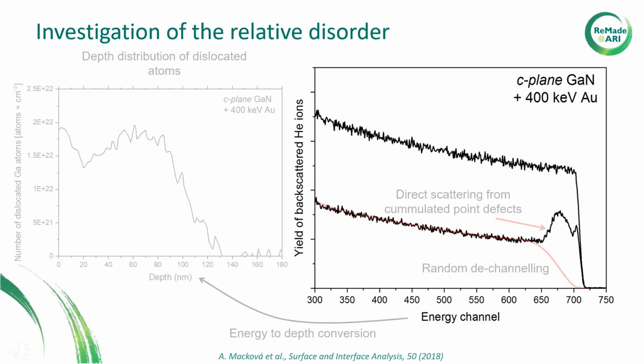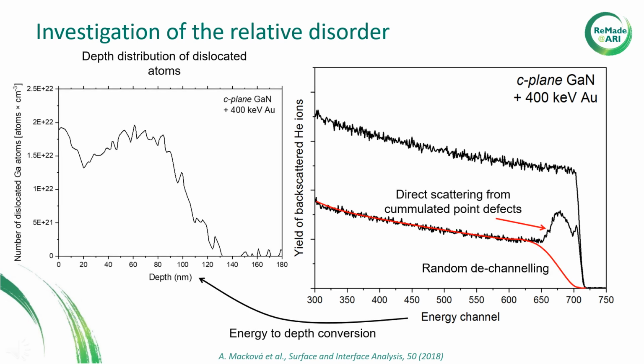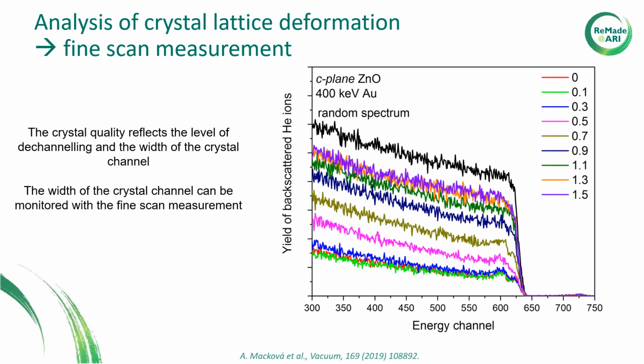The energy of backscattered ions corresponds not only to the type of the target atom but also to the depth from which the ions are backscattered. It is possible to estimate the depth profiles of densities of displaced atoms. The densities of dislocated atoms are estimated from direct backscattering, and thus it is necessary to exclude random dechanneling first. The crystal quality reflects not only the level of dechanneling yield but also the width of the crystal channel. The crystal disorder will lead to the deformation of the lattice channel, which can be monitored through the fine scan measurement.